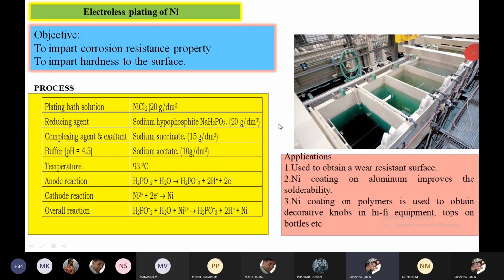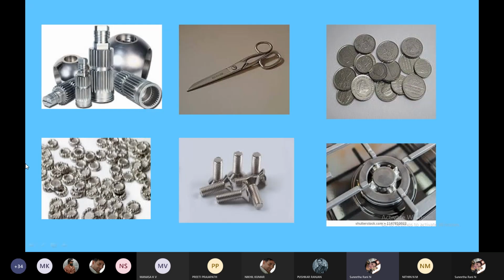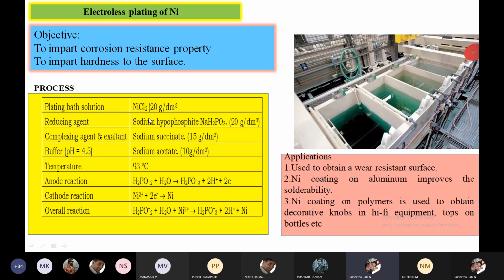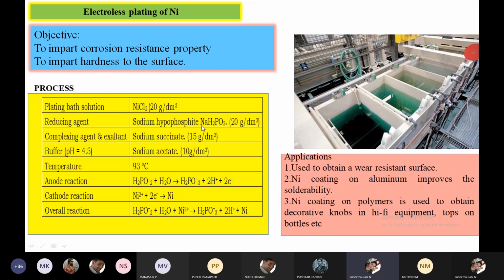The bath solution contains nickel chloride, 20 grams per dm cube, that is per liter. Next, we add the reducing agent, sodium hypophosphite, NaH2PO2, 20 grams per dm cube. A complexing agent and exaltant, 15 grams per dm cube. And a buffer to maintain the pH at 4.5. We add sodium acetate, 10 grams per dm cube.